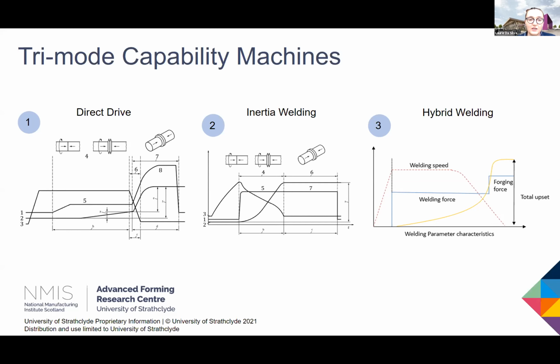So in direct drive or continuous drive, your energy is provided constantly through the motor. So you take your spindle up to a predetermined speed and you maintain that speed for a period of time before applying a brake, all the while applying an axial force through your fixture part. And conversely, in inertia friction welding, it's a stored energy input into the cycle. So a weighted flywheel's on the spindle. Again, you take the spindle up to the required speed, you disengage from the motor, and it runs under the kinetic energy of the flywheel until a speed of 0, all the while applying its friction pressure to create upset and form your joint. With both cycles, it's common practice that once you reach speed 0 and the part's cooling, you can apply a further forging force to consolidate the joint.